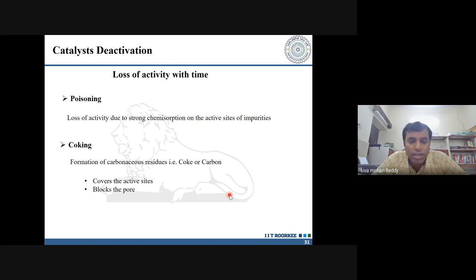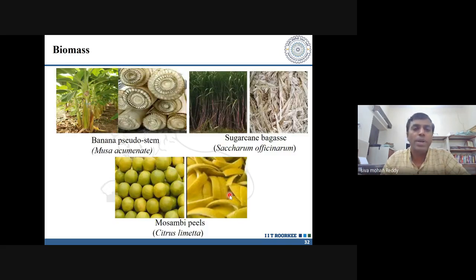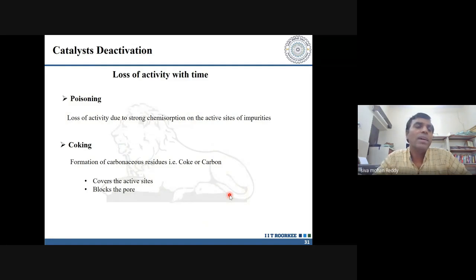Now the third and key most part is your coking process. Since biomass is a carbon source and you are using very high temperatures, the carbon that is generated during the degradation process sits on the catalyst surface, and coke deposition happens, which reduces the effective surface area and also the catalytic activity of your material. So these are the issues that are related to the catalyst.